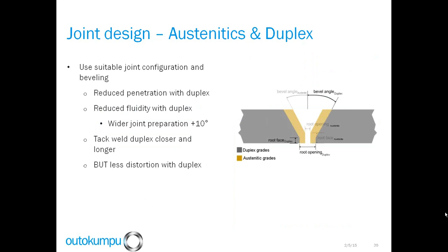And when we weld duplex stainless steel, we're typically going to use a wider root opening as well as a wider bevel angle. With the duplex filler metals, you're going to have less penetration. You're also going to have reduced fluidity with these types of filler metals. So these changes have to be made in the weld joint geometry.